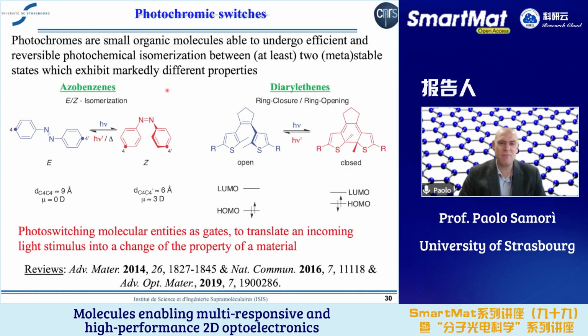which can be stable or metastable, and these states have different properties. So the most famous one is azobenzene, which can be switched from the more extended E form to the more compact Z form, and reversibly, one can go from the Z to the E, either thermally or with visible light. The two states have different dipole moments. Or you can play with diarylethene. Diarylethene is a molecule that has been developed by Professor Irie in Tokyo. And diarylethene has the peculiarity that you can switch from the open to the closed state with UV light, and you can go back with visible light.